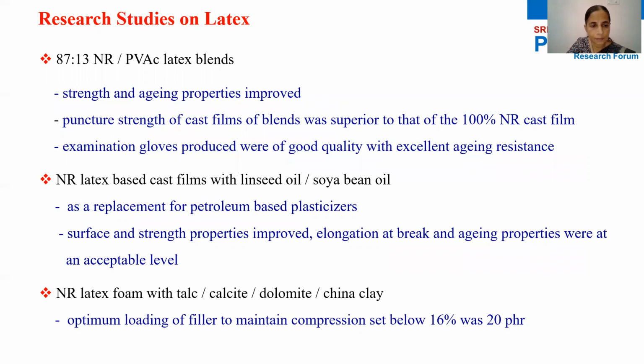In another study, natural rubber latex foam was produced with non-reinforcing fillers: talc, calcite, dolomite, and china clay. The optimum loading of filler to maintain compression set below 16% was found to be 20 phr. These fillers were loaded into natural rubber latex foam compounds with the aim of increasing the hardness and density.